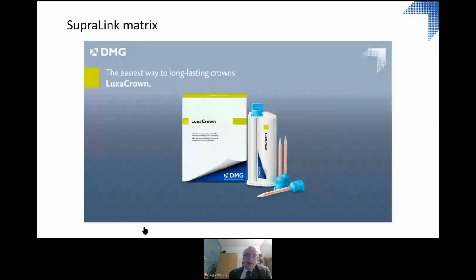Yeah, so this is the thing that we came up with, and it's part of several strategies for DMG products to increase the longevity of these materials, because the crack, no matter what material you have, is really their worst enemy. And while we cannot prevent cracks from starting, we can limit the initial onslaught of the crack formation, so that not every impact that would otherwise crack the material will actually do that by dissipating the stress within the material. And this is done by these molecular shock absorbers.